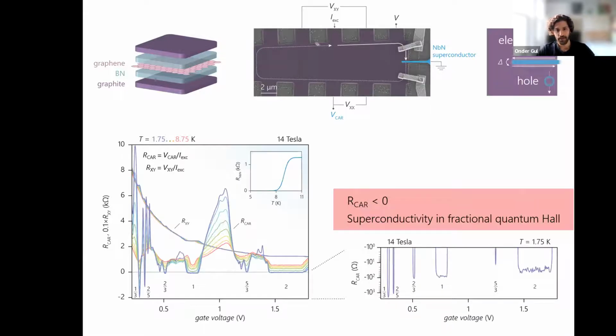A negative Andreev signal develops at several integer and fractional states. The signal disappears at high temperatures related to the suppression of superconductivity around 8 Kelvin, which is the critical temperature of niobium nitride at 14 Tesla. In the inset, you see the characterization of a niobium nitride strip of identical geometry as the one coupled to the device. So this is measured on the same device.